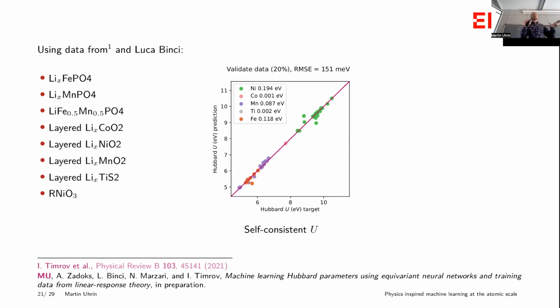So we have quite a diversity of electronic structures, so what the electrons are doing around the atoms, and that's what I wanted. I want to span as much of the space as I can. And when I train the model, and this is already on the validation data, so the data that the model has never seen, I'm getting errors that are, okay, 151 meV per atom. Well, what does that mean? Well, if you think these values are between 5 and 10 or 11, then 0.15 is already a very good result, more than enough for what is typically used in these self-consistent calculations.